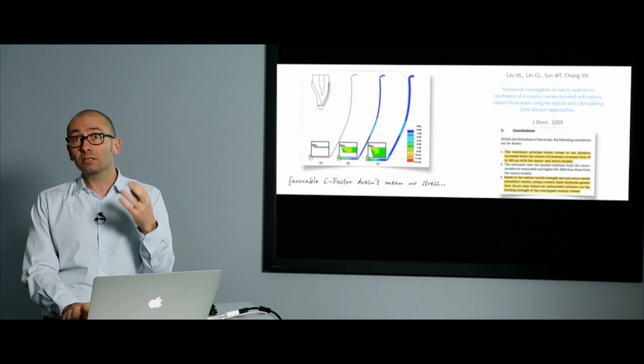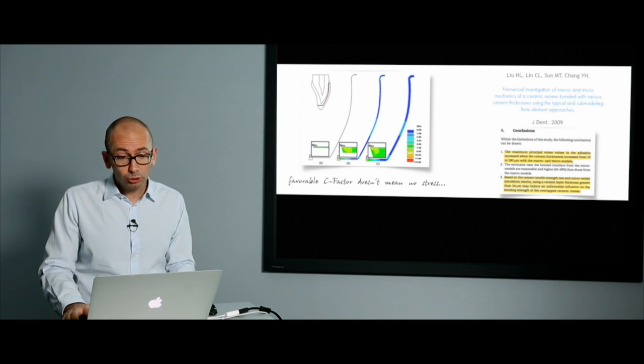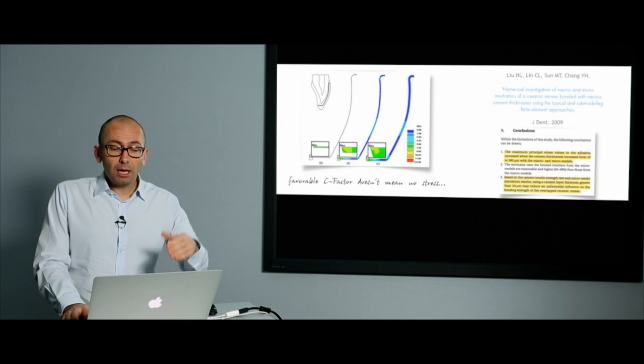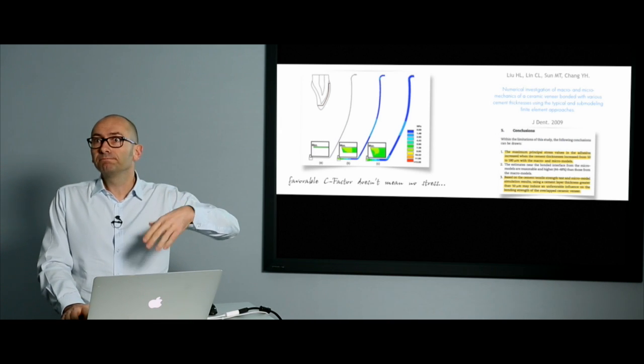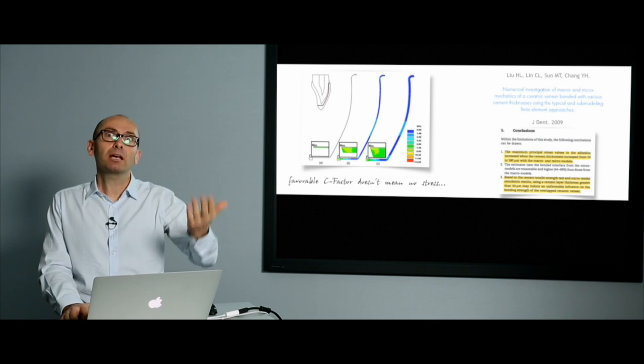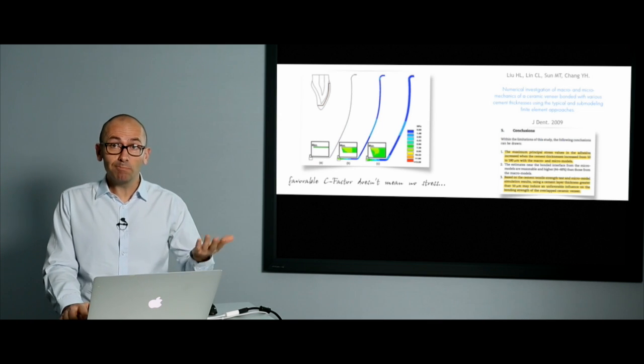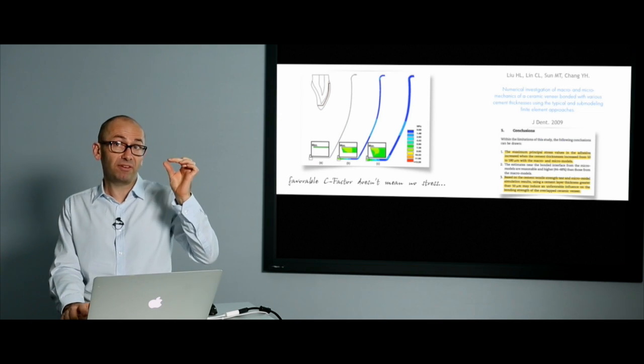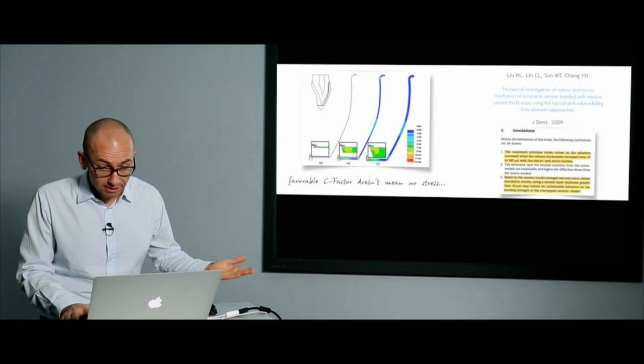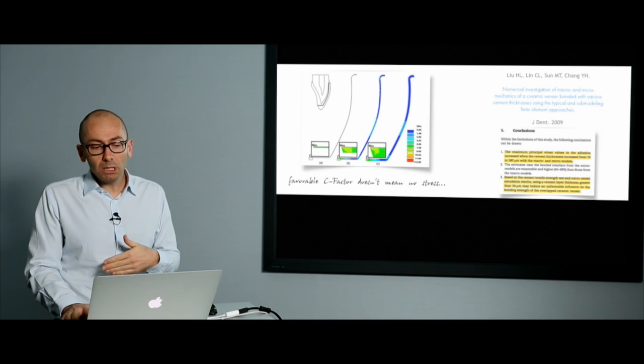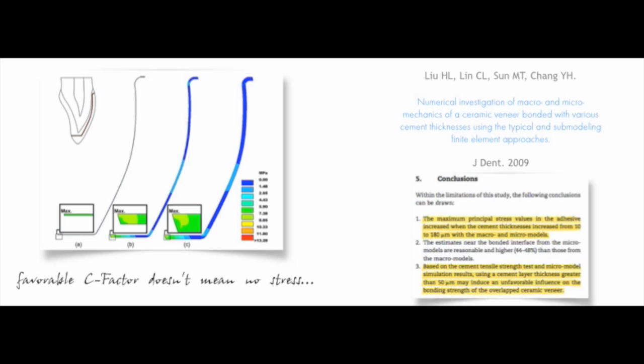So this is a factor that we have to take into consideration, unfortunately, because if the thickness is more than 30 or 50 micrometers, which is nothing. It's impossible to get a margin of 50 micrometers with a composite resin anyway. We have usually between 200 and 400 micrometers thickness for our cement, which is huge, and with this kind of thickness, you will have shrinkage and tension.